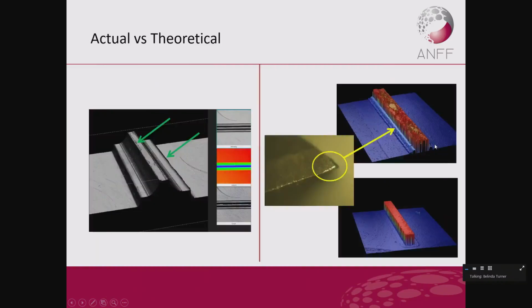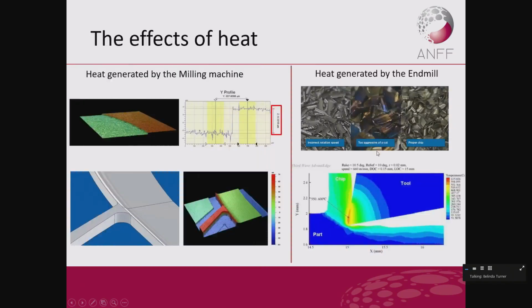We get other problems, like these two images here. That was the same CAM program, sorry. It's just that on the top one, the tool was worn. So this little bit of wear on the tool edge caused it to look like this under the scan. It obviously took the edge off, so it wasn't sharp, so we had these radii in the bottom. When we reran it with a new tool, we got this nice clean geometry. So we often have to rerun parts, and we'll be inspecting them in the process to check that what we've made is correct before we take it off the machine and send it to the customer.